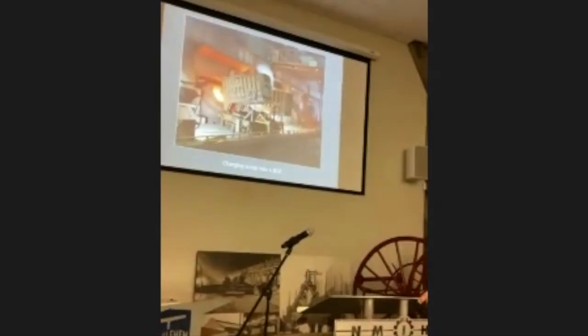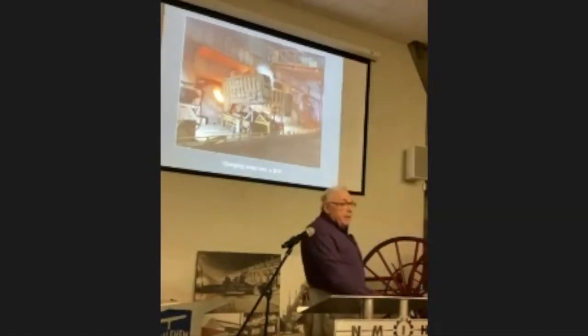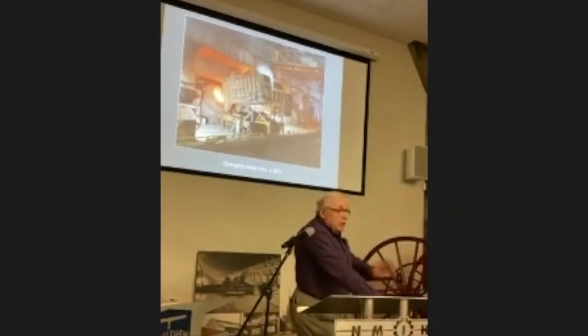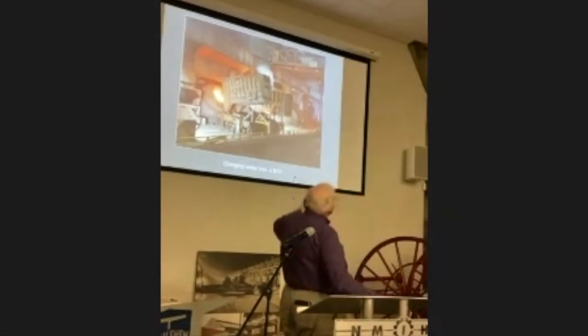More people at work. Charging scrap into the basic oxygen furnace. The basic oxygen furnace took a charge very similar to the open hearth furnace, approximately 50% scrap, most of which you tried to generate in the mill, so you knew what it was, and then 50% hot metal from the blast furnace. So the scrap goes in first, and then the ladle comes to charge the hot metal.